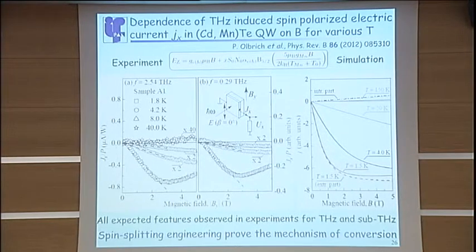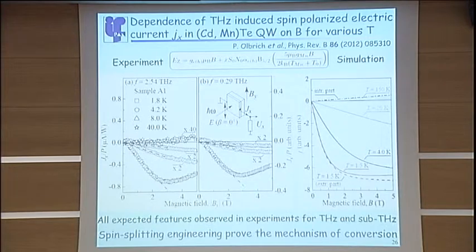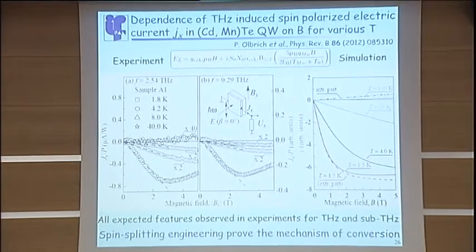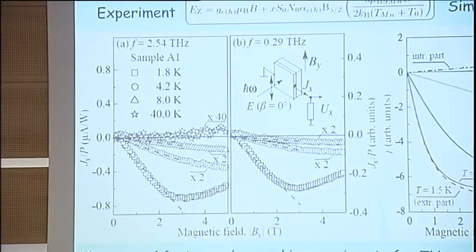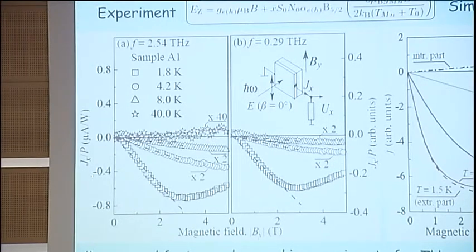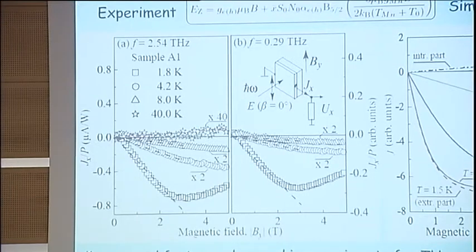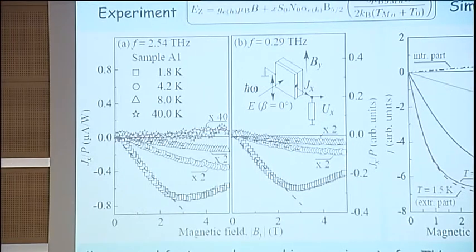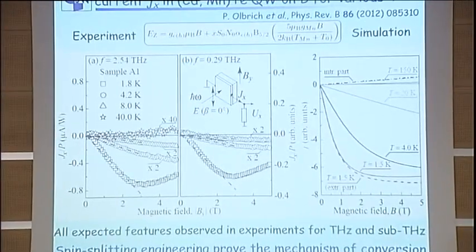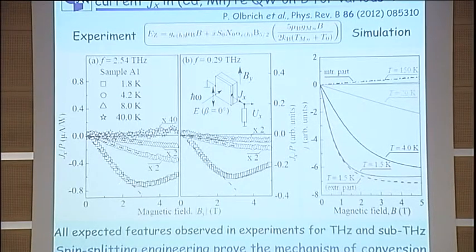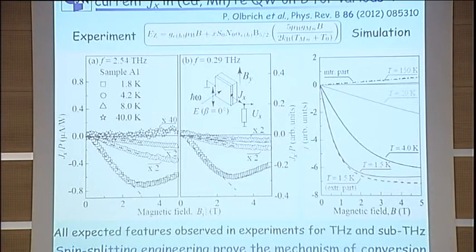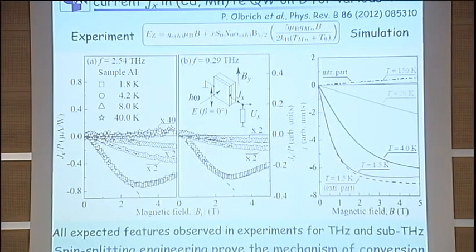And this is demonstrated in this viewgraph, showing the data for a terahertz far infrared laser and a sub-terahertz carcinotron experiment. You can clearly see that there is a very strong current induced in the configuration that I have shown before, when you have the sample at very low temperature. Now, if you increase the temperature, this gets smaller, and that is because the exchange contribution has the temperature dependence of manganese here, so the exchange g factor gets smaller, and the effect gets weaker. In the case of low temperature, we have a gigantic current because of the gigantic spin splitting. Now, if you raise the temperature much, much higher, then this is very small, and the intrinsic g factor takes over, and you should have a change of the sign of the generated current.